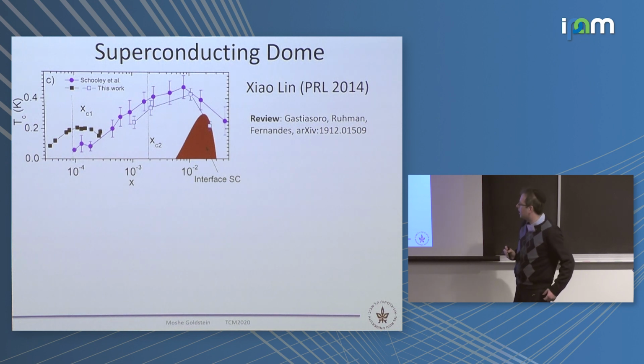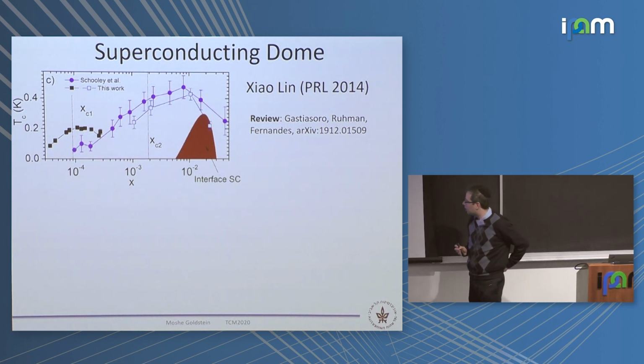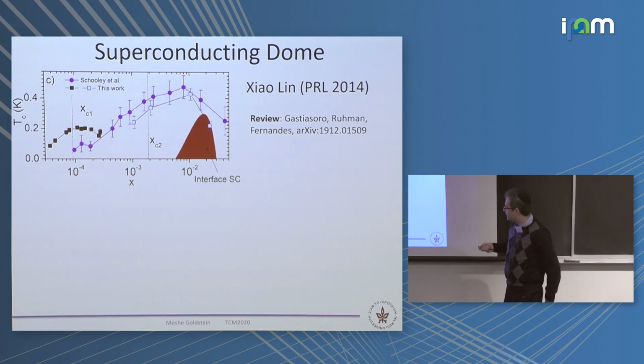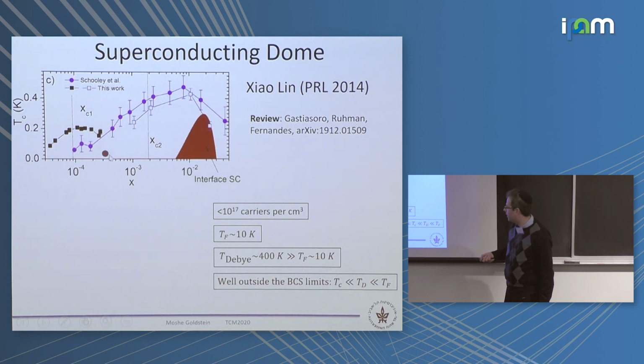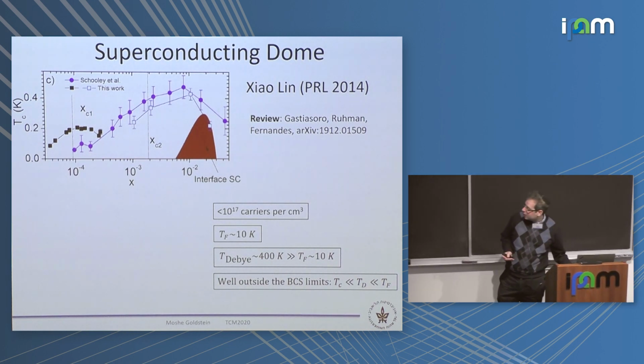Now, when you dope it, it not only becomes a conductor with these orbitals, it actually becomes a superconductor. And this is a very peculiar superconductor. As a function of the doping, the critical temperature is non-monotonic. It increases and decreases as a function of doping. And also it's unusual in many other ways, because the carrier density can be below 10^17 per centimeter cubed, and still it becomes a superconductor. It's one of the most dilute superconductors known. And the unusual thing is that the Fermi energy is very low at those concentrations, and it's much smaller than typical phonon frequencies. So this is well outside the usual BCS limit. In that sense, it could be similar to things discussed in bilayer graphene and other systems.